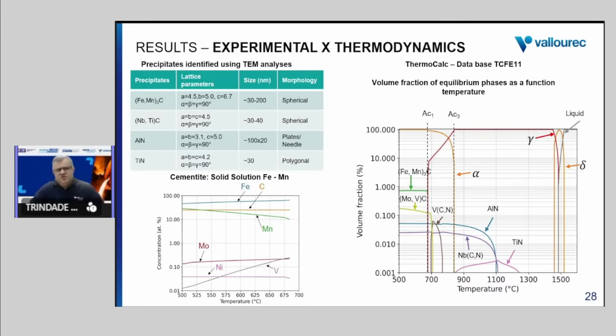Additionally, here is cementite. Just additional information: cementite here is really as observed. We have observed cementite that is very rich in manganese atoms in solid solution, and the thermodynamics also predict this high solubility of manganese in the cementite.